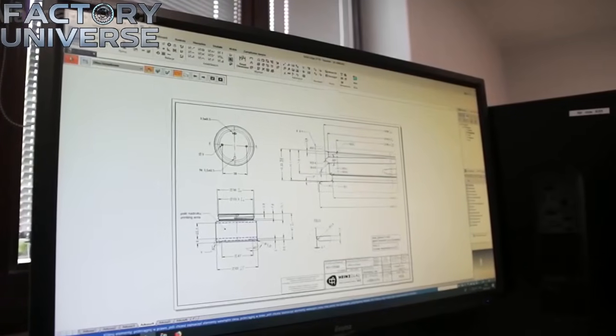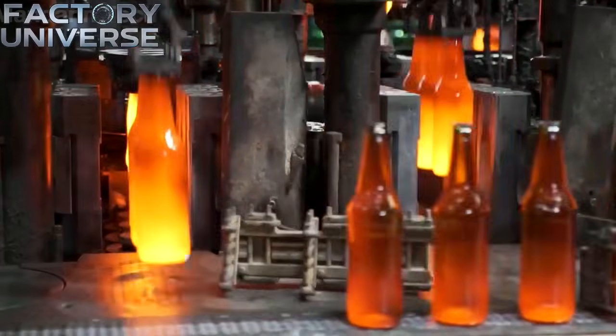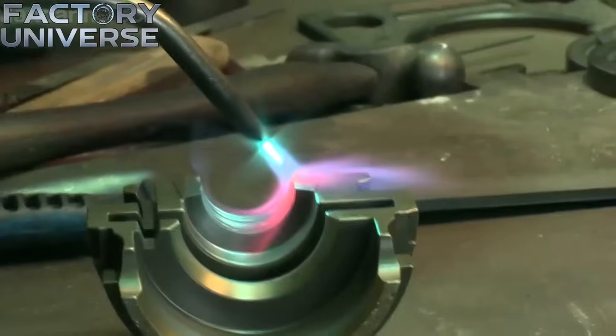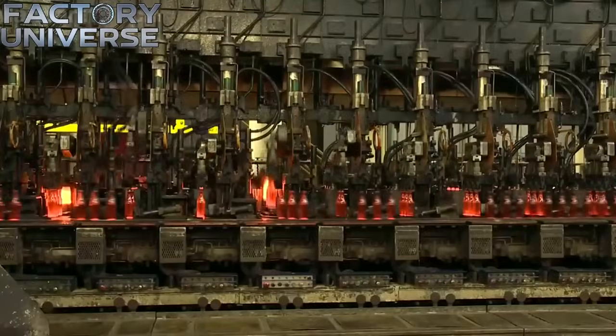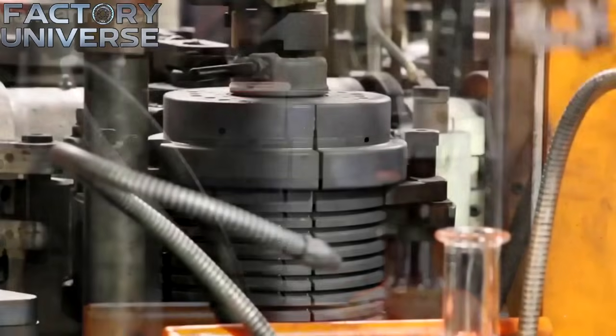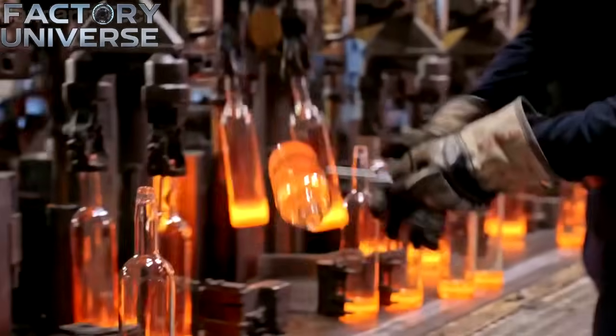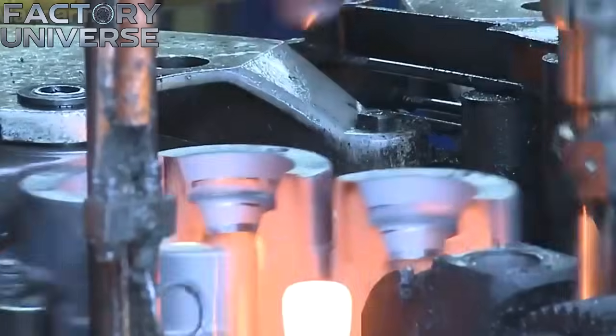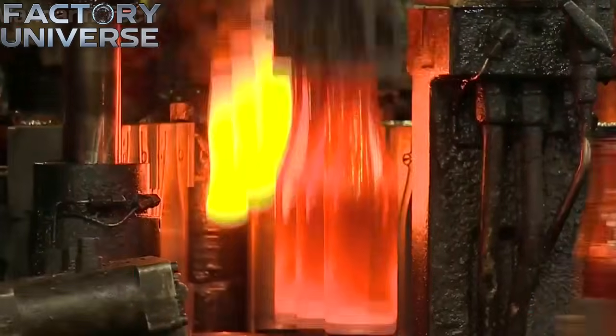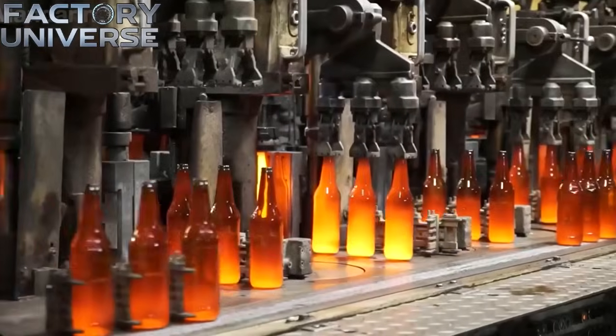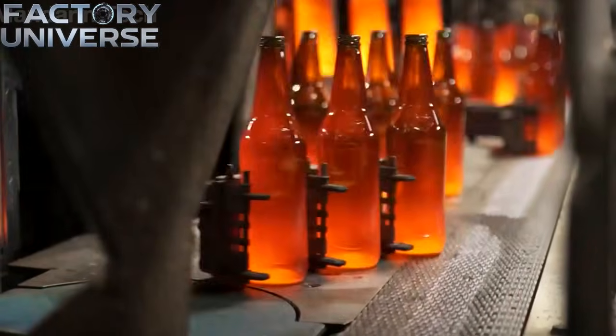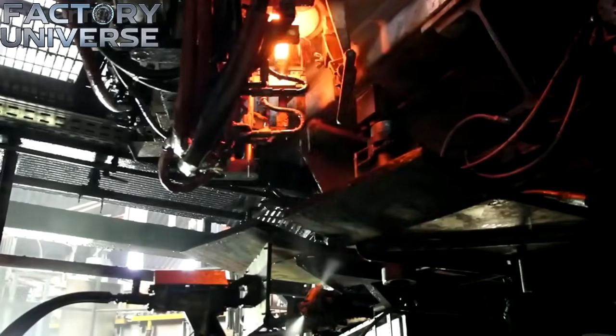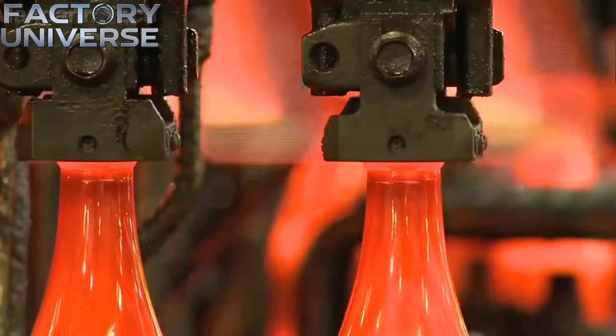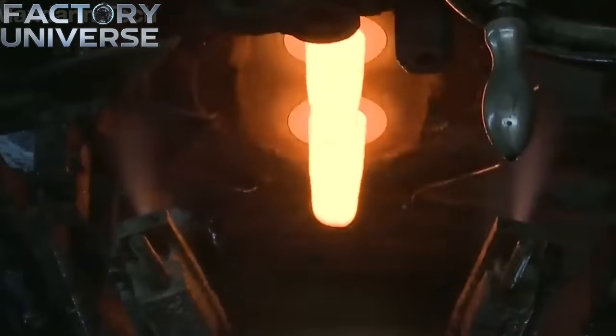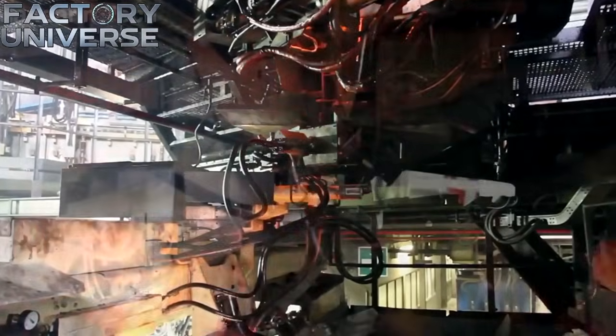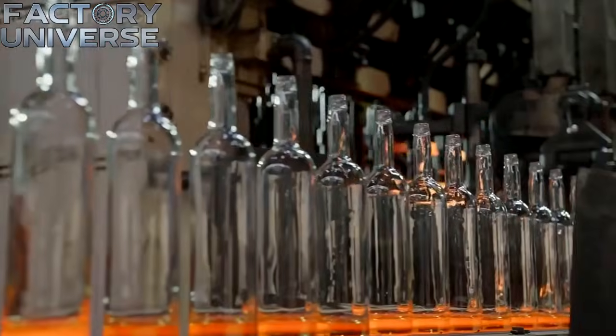Everything only gets more complicated. Specialized technicians install the completed molds into the double blow production line, a system recognized as one of the most reliable methods for manufacturing hollow glass products like food jars, pharmaceutical containers, and soft drink bottles. It is visible how the forming process begins with the release of molten glass segments known as gobs into the initial blank mold. These gobs are severed from a continuous liquid stream at temperatures of approximately 1,100 degrees, a thermal state that ensures the perfect viscosity for smooth and consistent shaping.